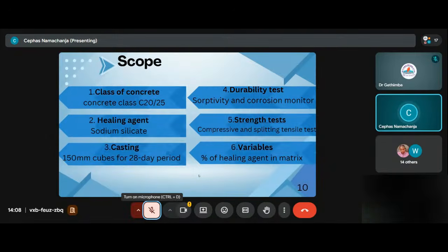We'll also perform mechanical and durability tests. We will simulate a chloride condition environment where we will expose our pre-cracked molds through a repeated cycle of partial immersion in 3.5% salt water, followed by air drying periods. The entire testing procedure will span a period of about 6 weeks.